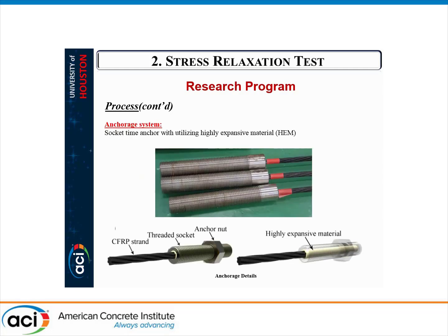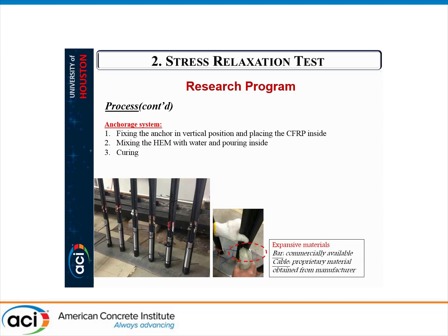The anchorage system that we used is the socket type or bond type anchor, which is a threaded steel pipe filled with highly expansive material to generate the expansive pressure uniformly through the length of the anchor to enhance the bond and reduce the slippage and losses. So the production of the anchorage system was conducted in 3 steps. First, we placed and fixed the CFRP tendon at the center of the anchorage system, and then after mixing the expansive material with water and pouring the expansive material inside the anchor, we let it cure and set for at least 24 hours to generate enough expansive pressure inside.